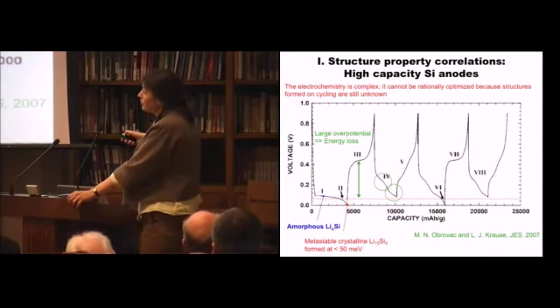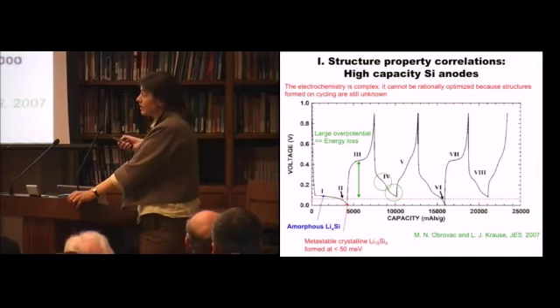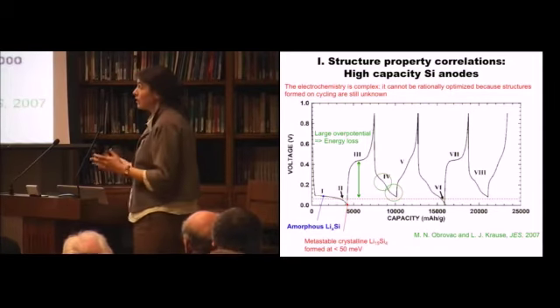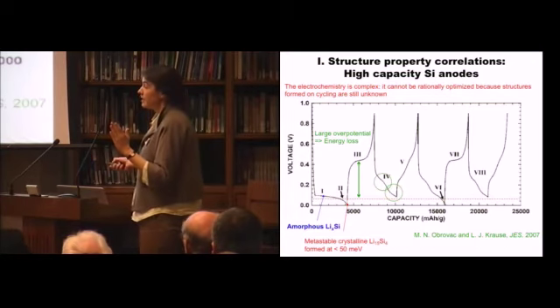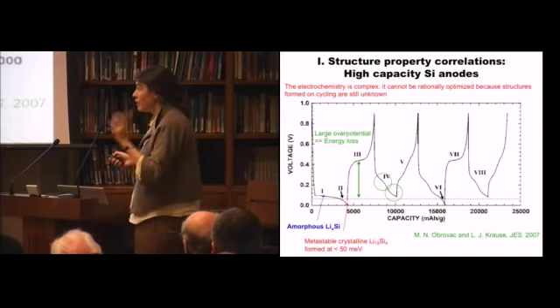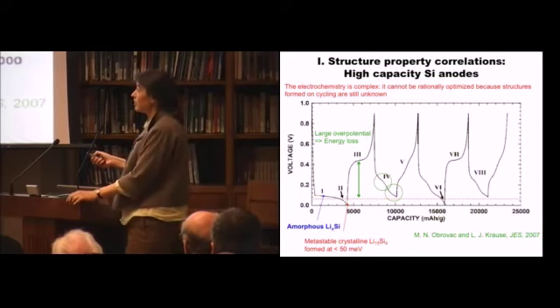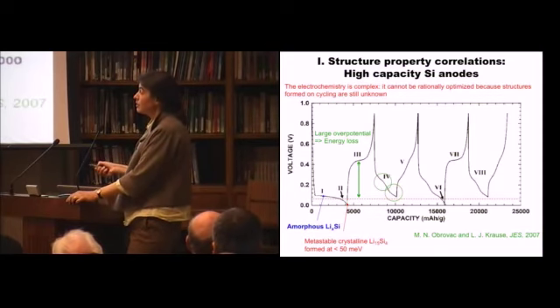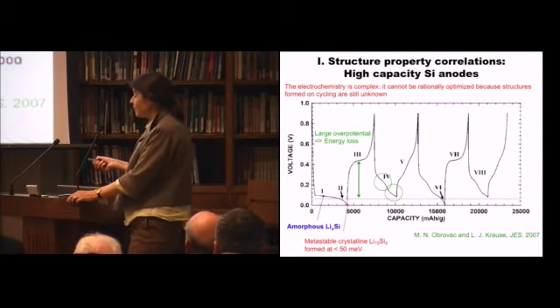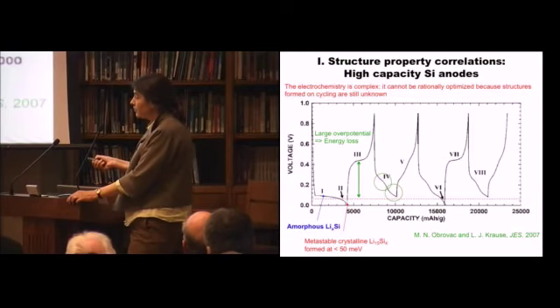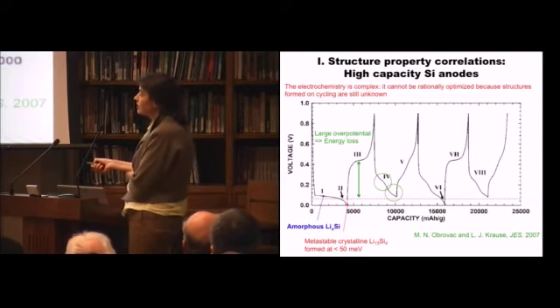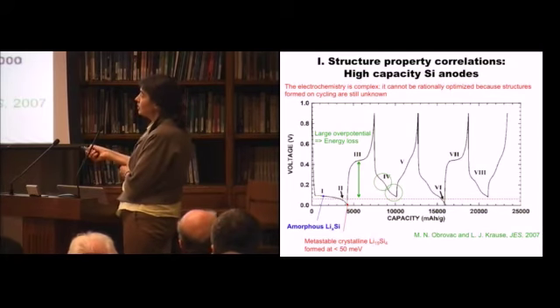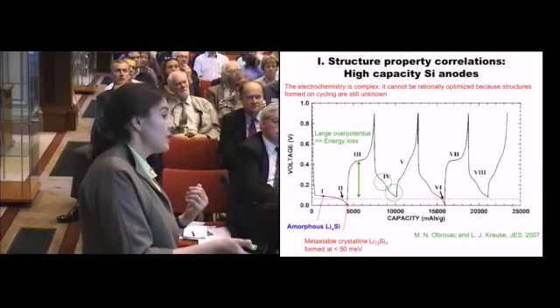Let me walk people through these types of plots. In an academic lab or in an industrial research lab, you don't typically research the whole battery. You typically make up a material with, in this case, silicon on one side and lithium metal on the other side, because you don't worry about the safety issues and you can control it. It allows you to see what's going on. Then I measure the voltage as I insert lithium into the material. The silicon reacts with lithium at about 150 millivolts. It starts with crystalline silicon, it goes amorphous, and if you go down to close to 0 volts, then you form this metastable crystalline phase. As you charge, you can see the voltage as you pull the lithiums out of the structure is quite different from that in discharge.